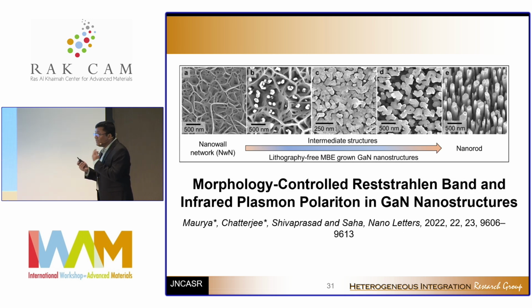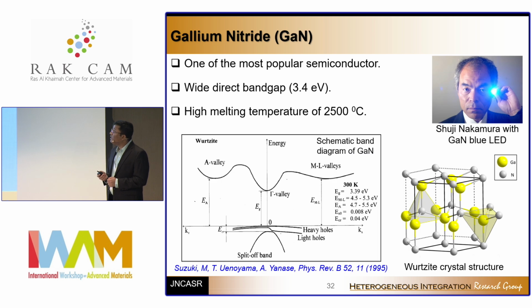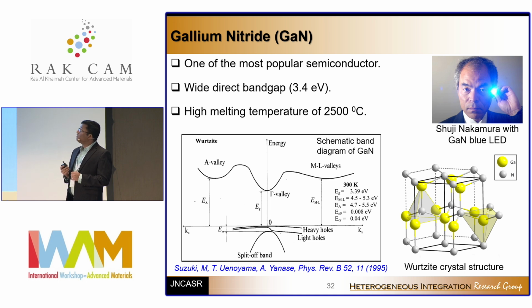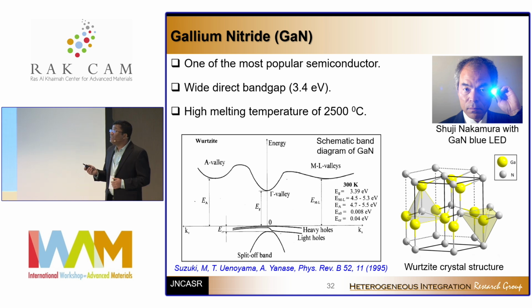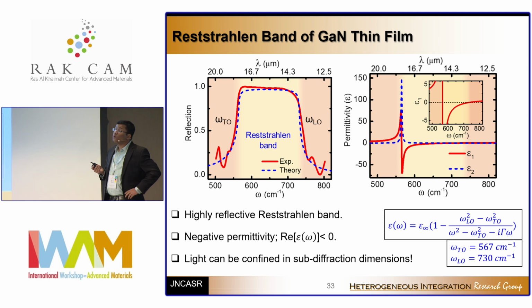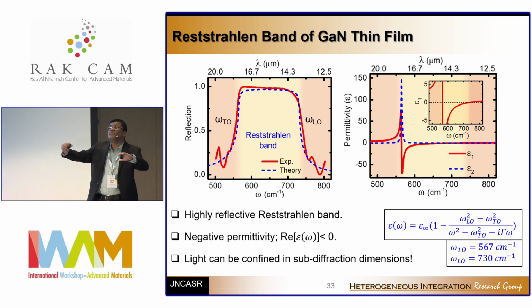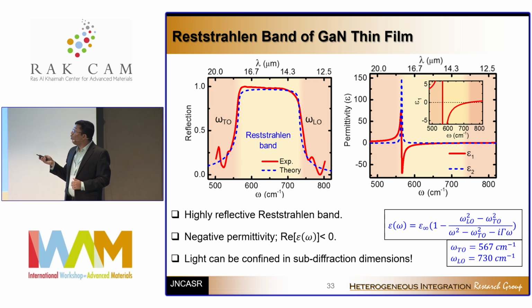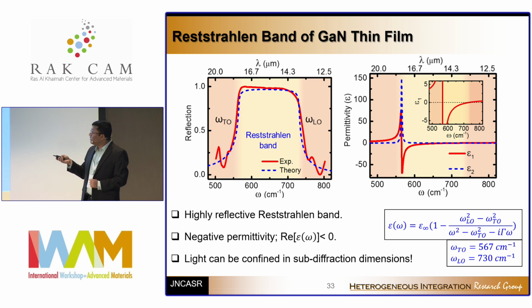Now, along with scandium nitride, we have also looked at gallium nitride. I'm pretty sure this audience does not need any introduction to gallium nitride, but let me just say that gallium nitride is a wide bandgap semiconductor, 3.4 eV. What is perhaps a little less appreciated is that gallium nitride is also an extremely good polar semiconductor. If you take a perfectly flat film of gallium nitride, it would also show a very high quality Reststrahlen band with reflection reaching almost 1 and negative permittivity between the TO and LO phonon frequencies. That just comes out of its normal condition, but it's also boring.